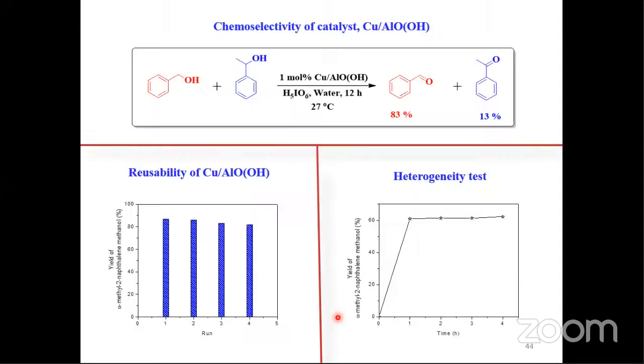So again, it is demonstrated that the nanocatalysts are selective and also active, and you see here 95% of this ketone is formed from this alcohol, right? And some of the alicyclic alcohols were also tested. Here the yield is very low because this is a sterically hindered substrate, and of course whatever catalyst you use, this conversion is always less efficient.